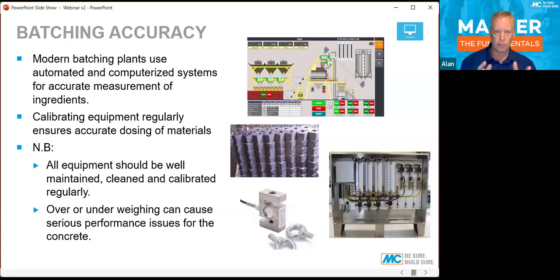Our beautiful admixture dispenser there in the bottom right corner is fine, but we need to clean it regularly to make sure we're not over or underweighing. If we don't, then we can have serious performance issues for the concrete. Either we'll get rapid slump loss or maybe extended setting times. In some cases where the equipment's neglected, the dosing of retarders has meant that concrete doesn't set for 2 to 3 days. And on a residential project, that's not good.